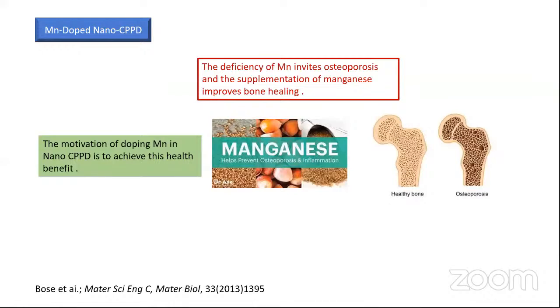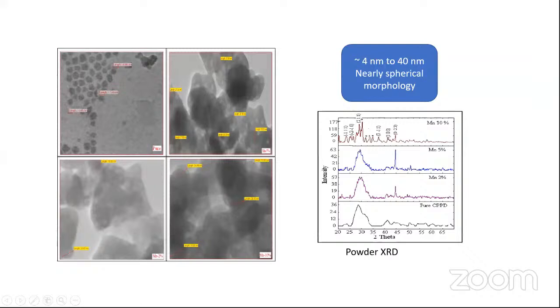Then we have doped manganese in nano CPPD. The deficiency of manganese invites osteoporosis, and a supplement of manganese improves bone healing, so it is a very important one. This is the healthy bone, and another is the osteoporosis affected bone. You can see that the porosity increases in the bone. So the motivation of doping nano CPPD is to achieve this health benefit. The manganese health benefits were reported in 2013. The left-hand side shows TEM images of manganese doped CPPD, and the right-hand side shows the powder diffractogram.